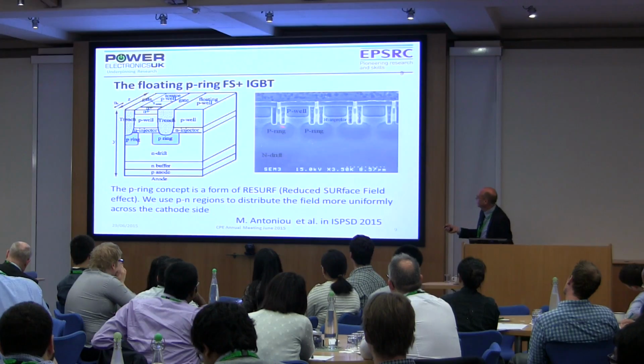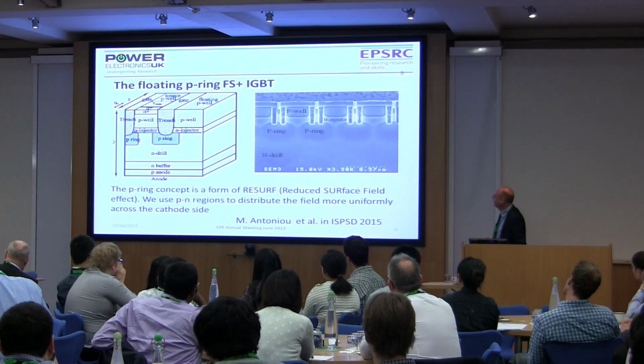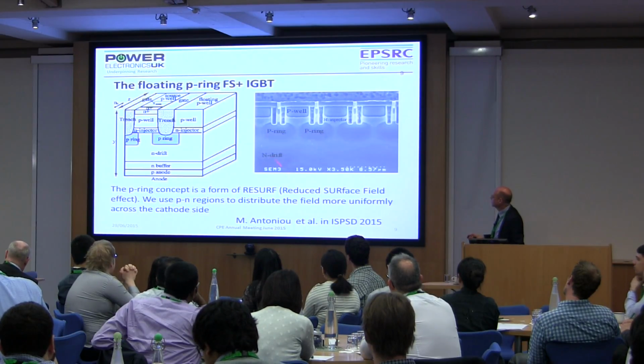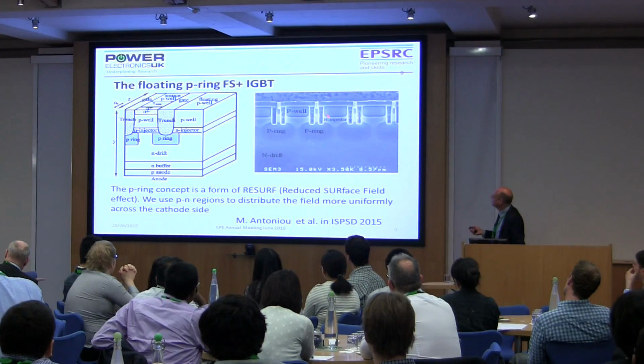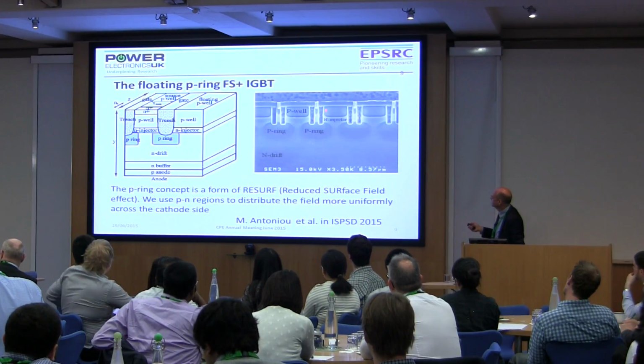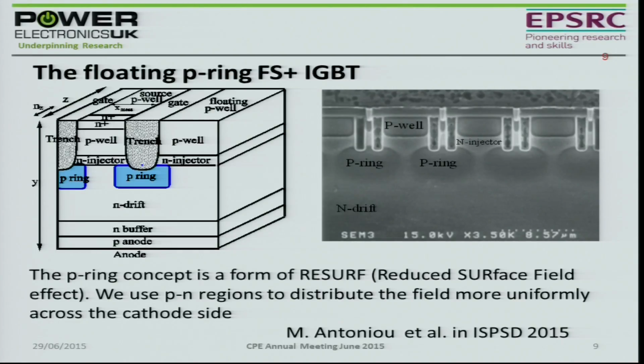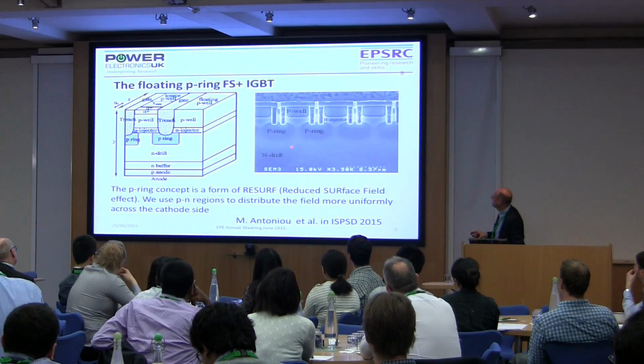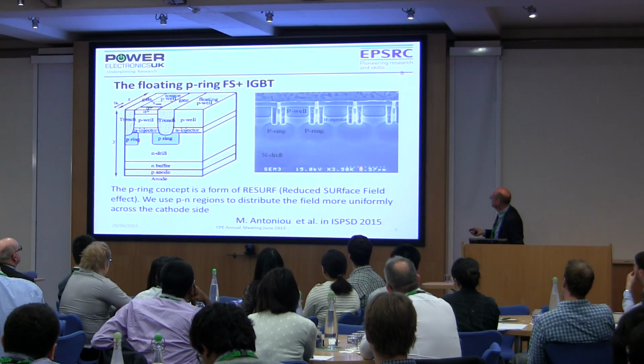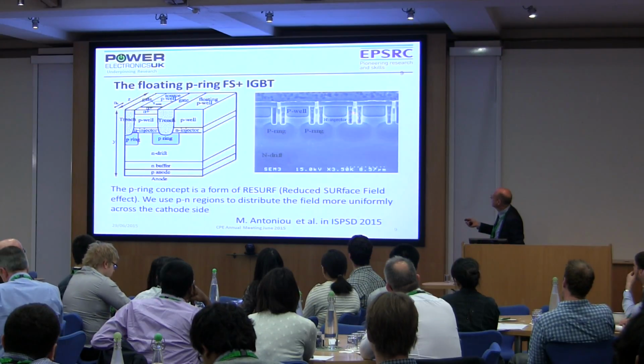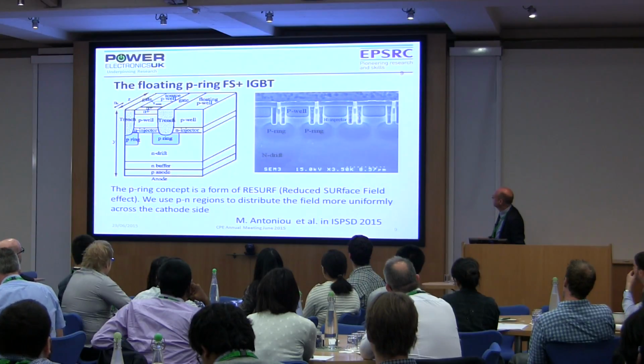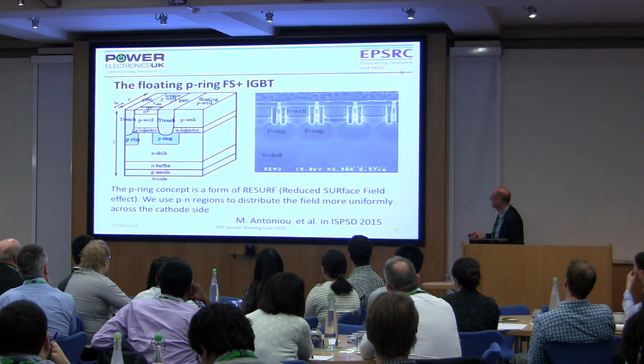This is an SEM or TEM picture of one of those structures, actually an SEM it says there. But you can see there that you've got double trenches here rather than a single trench there. P-rings at the bottom, and there's the N+ injector there. And you can see that these feature sizes are submicron features. These trenches are very, very small indeed.